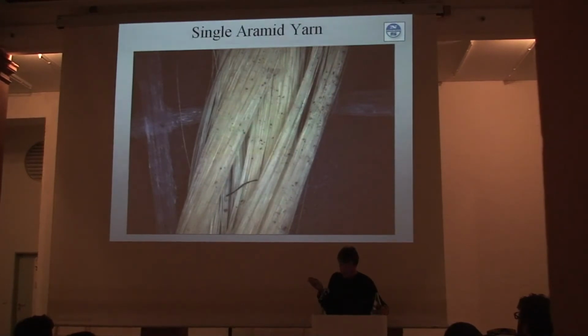The interesting thing about this is that in terms of the material's property known as modulus or stretch resistance, as opposed to strength, so those are different properties. Resistance to breakage is strength, resistance to stretch is modulus. This individual filament is about 15% better than that bundle. So for us, or for those in performance sport, when the whole goal is to make something as light as possible and as stiff as possible, this 15% is potentially a revelation here. So to use an existing material and be able to get 15% more mechanical properties out of it, or stretch resistance, is quite a big deal, and was the goal of spreading this out into a tape.